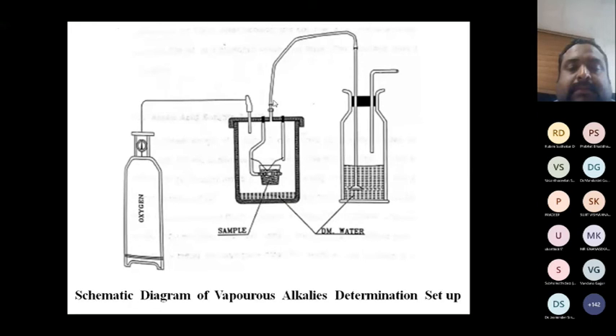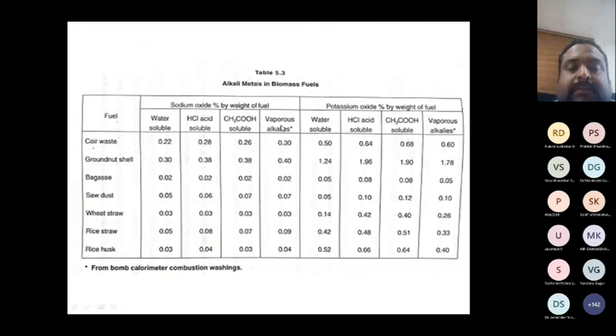It gives a direct measure of vaporous alkali, because in the bomb calorimeter experiment the combustion temperature inside is high, so the entire vaporous portion comes out. I try to measure the alkalis from these two washings, the DM water and this water. That is also what I added here as vaporous alkali, collected straight away from the bomb washing. So the water soluble, acetic acid soluble and hydrochloric acid soluble fractions of sodium oxide and potassium oxide are the things I measured during my research project. So this is a direct measure of vaporous alkali. These others are indirect methods, water soluble and acid soluble, where we assume these are all vaporous alkali. Instead, vaporous alkali is directly measured by the bomb washing method.